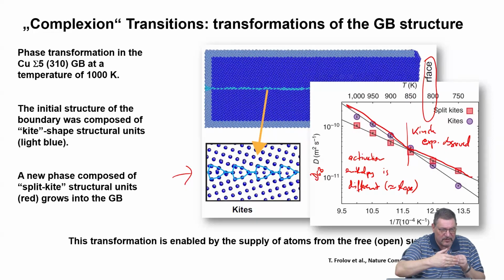Any of these transformation fronts tend to accelerate the measured diffusion, because it's not only thermal diffusion then, but it's also this transformation process and locally created excess volume which drives the mobility of the atoms. But it's then a different contribution to mass transport, which we normally wouldn't describe as a pure diffusion process, because there's more than just the response to random motion because of temperature.